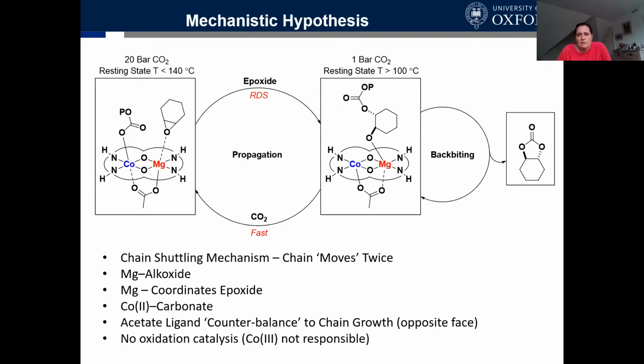And so this is something we've called chain shuttling, but we also believe is a very critical feature of why these catalysts perform well. In essence, they are set up in their coordination geometry to accelerate this chain movement. The acetate ligand that is also coordinated by this catalyst, shown on the opposite face to the polymer chain, is important and plays a role in facilitating chain shuttling. There is no oxidation of the cobalt during the catalysis, so cobalt-3 is not present.